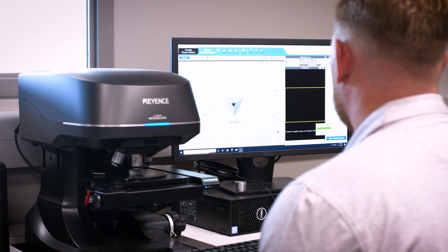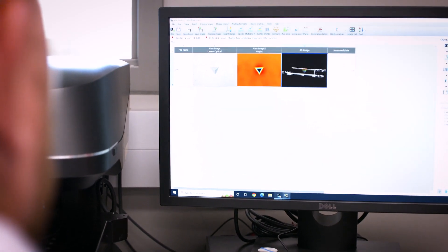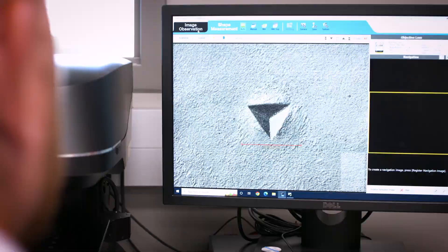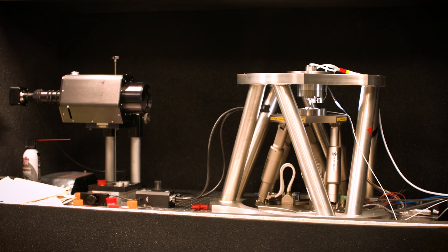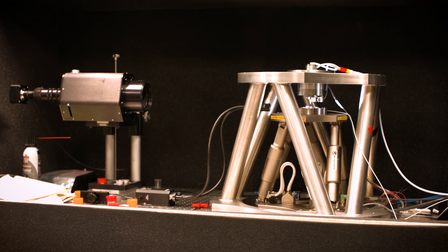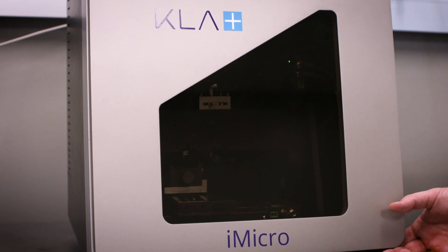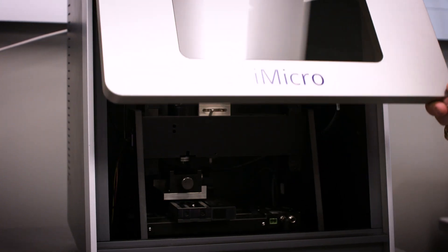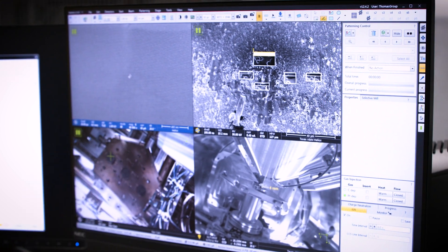As a result, we can get to much higher strain rates. A big thing about nano indentation is you're able to probe small volumes of material very quickly. As a normal large scale test at high strain rate, you may only be able to do one or two tests over the course of an hour. We're able to do hundreds of tests on the order of an hour or two. It's really given me an opportunity to experience new sample preparation and imaging techniques, whether that be ion milling, laser confocal microscopy, AFM, or SEM, to get really good images of these very small indents.